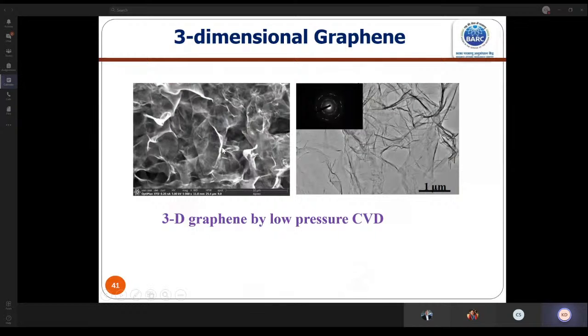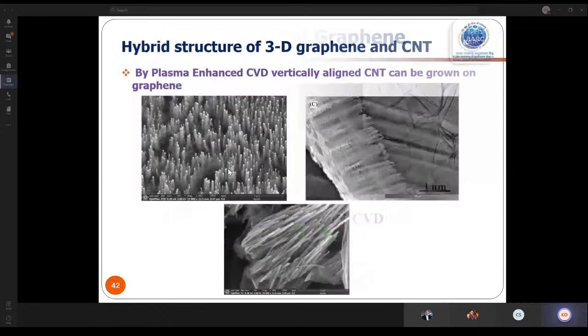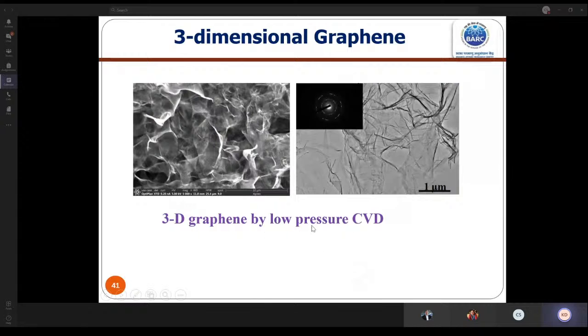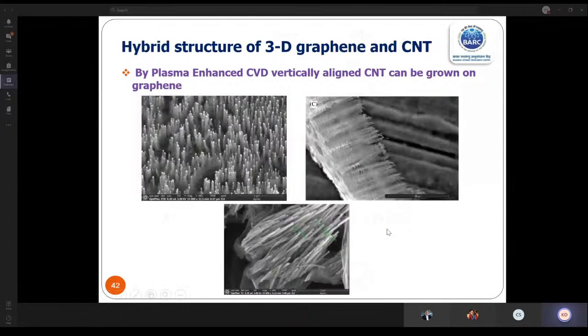I have shown an electron microscopic image where we can have very high porosity. So what is the application? I'll tell at the end. This 3-dimensional graphene can be developed by a method called low pressure chemical vapor deposition. We can also develop a hybrid structure. It's very interesting. Once we have 3-dimensional graphene, on top of that we can grow carbon nanotubes which are highly aligned, by plasma enhanced CVD. So it is a hybrid structure. Bottom side is three-dimensional graphene, top side is aligned carbon nanotube. They have very specific sensing applications, and also for supercapacitors.